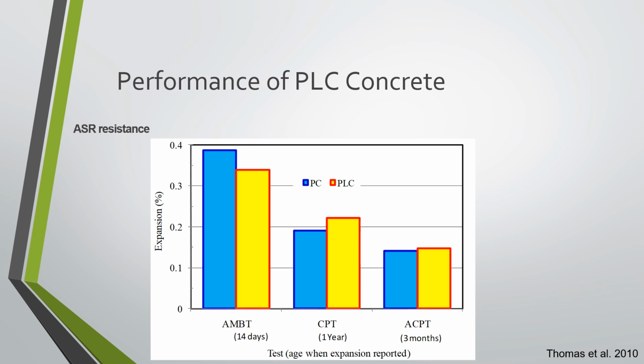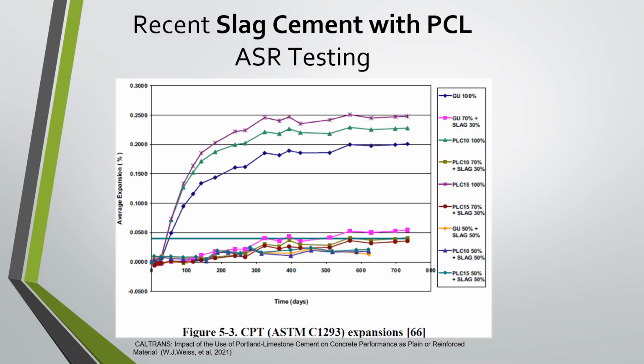ASR, we're seeing similar results. And this was from the 2010 with Thomas. So here are some results that are also showing from Caltrans. Because a lot of the data that was done in 2010 by Professor Hooton and Thomas, right, that's been in use, and we've been using that in North America, especially in the Great Lakes area, because we're so close to the Canadian side, and a lot of Canadians were already doing the same thing, right, this testing. However, Caltrans wanted to do their own testing, so they reinvented the same wheel that happened before. So these are the same results showing that PLC was able to do what it was doing.